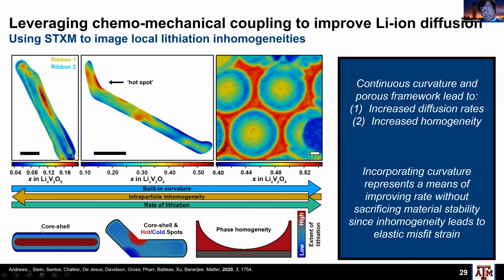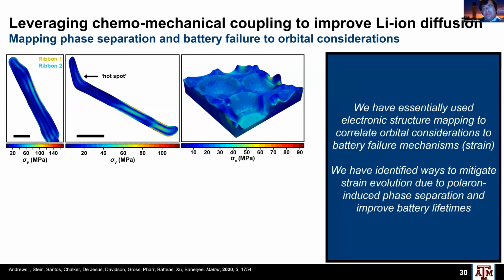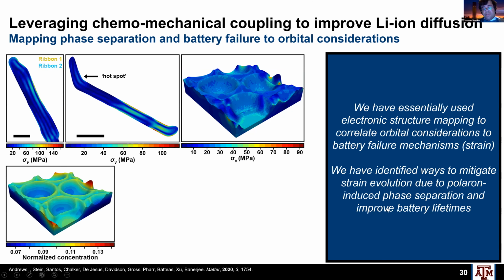So either elastic misfit strain results from core shell morphologies for straight nanowires, or because there's hot spots and cold spots that form across these wires. So having this curved cup-like architecture gives us really beautiful, homogeneous lithiation at high rates. Very high rates of lithiation are also possible. So we've essentially used electronic structure mapping to correlate these orbital considerations to battery failure mechanisms, and then identify a way to mitigate it and to improve the lifetimes of batteries.